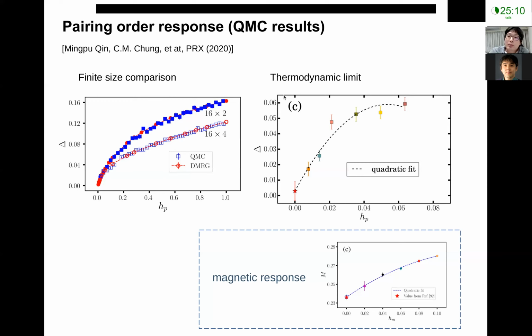But if you do the same analysis on the magnetic field - applying a magnetic field and decreasing it to see what the magnetization is at zero field - you get pretty good behavior all the way to zero field. This zero field magnetization is perfectly consistent with the pure quantum Monte Carlo method, so this is actually a pretty good way to analyze the system.